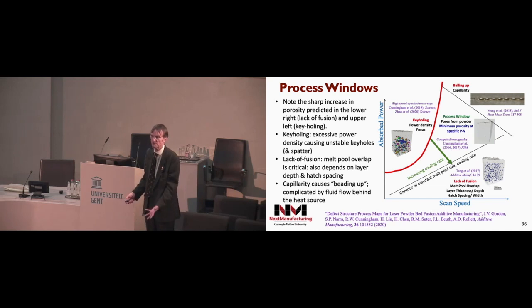So there are two major sources of porosity, and in between, you have a good chance you should be able to have a parameter space in which you can run the machines and be confident that you'll get not exactly 100% dense, but at least a pretty substantial fraction. But for those of you interested in research problems, I can tell you that the beading up or balling up problem up here at high power and high speed is still there. We still don't really understand it very well. It's an opportunity for physicists as well as for material scientists.